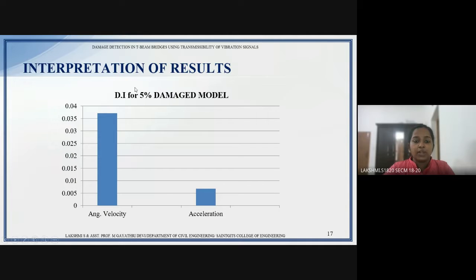So the obtained result was plotted in the form of a graph, and we can see that there is a higher value of damage index being shown by the angular velocity, whereas the damage index calculated based on acceleration is having a very small indication only. So the higher damage index value shown by the angular velocity indicates that the obtained signals and the corresponding results are very much strong and indicative also of the nature of the damage at that location, which cannot be very efficiently determined using the damage index calculated using acceleration.